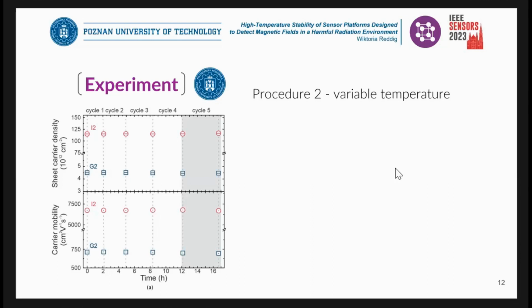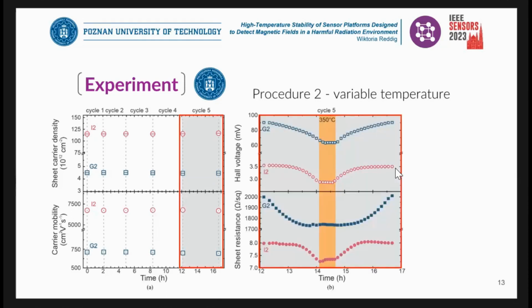But let's see what happens in between the cycles using the example of the 5th cycle. Here you have sheet resistance and Hall voltage, so the pure things that we measured of both of the samples. The graphene one, of course, they do change. However, the graphene changes more uniformly. The changes are maintained throughout the whole cycle, and the indium antimonide experiences a sudden change around 200 degrees Celsius, which is connected to the fact that this material has a melting point at 525 degrees Celsius. So the closer we get to this temperature, the more sudden changes we will expect.